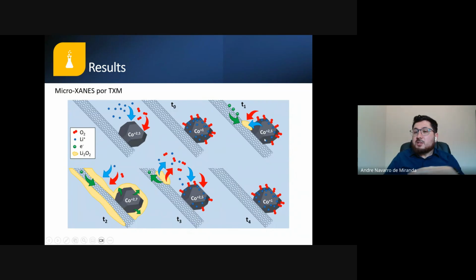Then when we start to discharge the catalyst, we start to form here lithium peroxide, and then the particles or the atoms or the ions that have been absorbed for the cobalt start to go out and form this really big film of lithium peroxide. Then when we start the charge process, the lithium peroxide starts to decompose to the electrolyte, and then these particles continue to absorb these atoms, these ions, and then it goes back to the cobalt plus one oxidation state.